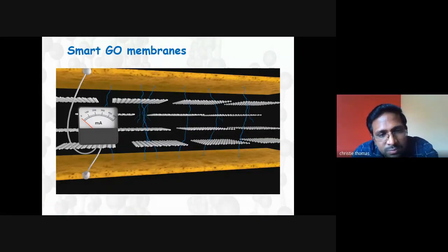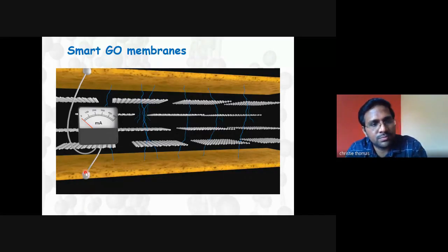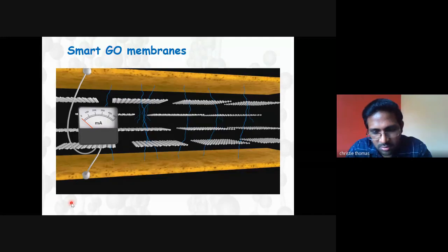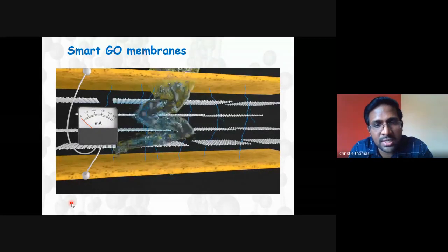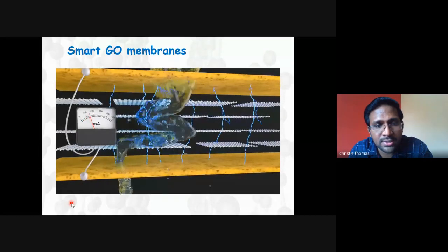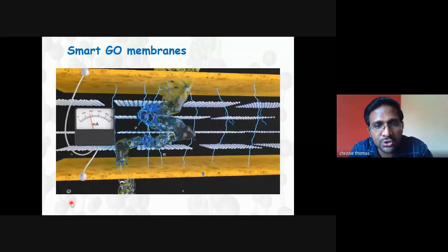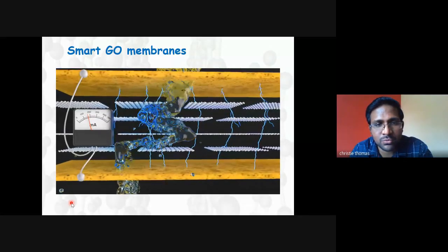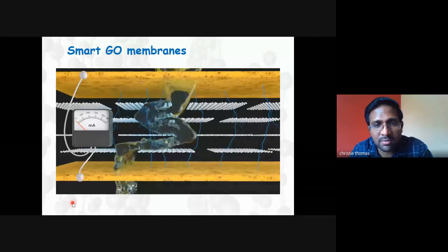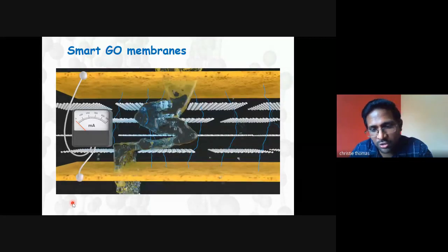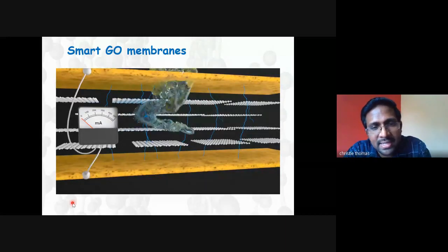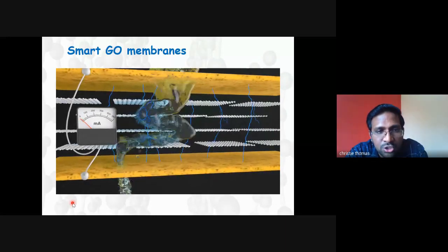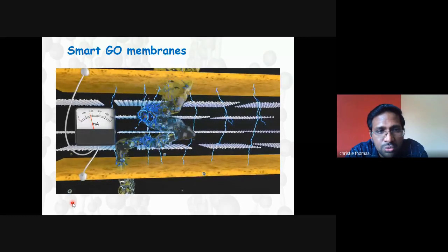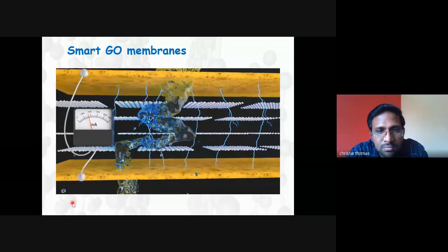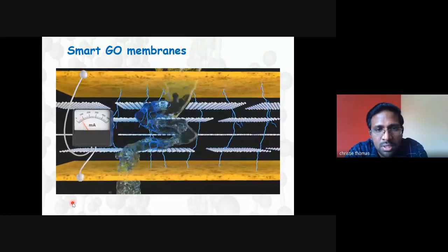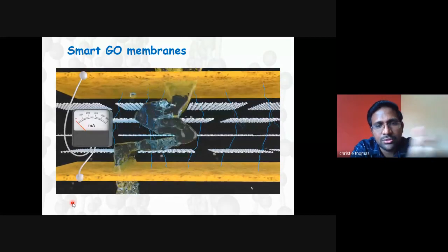So what we observed was, I will play this video. You can see here water is going through when the current is 0, but when the current is increased, you can see water permeation stopped. Okay, and when the current is reduced to 0, again water permeates. I will play it again. So you can see water flow going through at 0 milliamperes, but when it increased to 200 milliamps, the water permeation stopped. So that's what we observe.